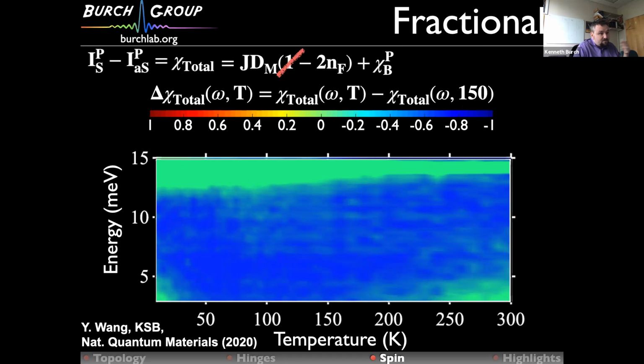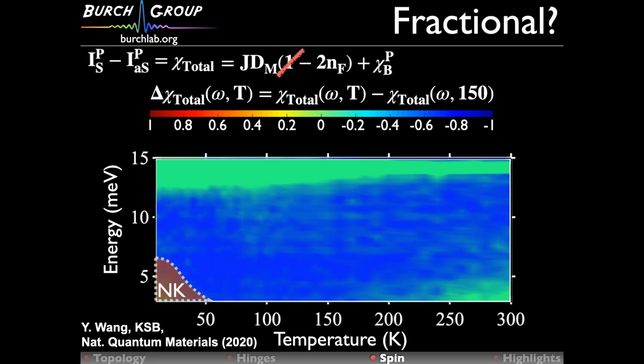And what we find is perfect agreement, except of course near the phonon, because there's no phonon in their calculation, and also in this small region at low energies and temperatures. And that enhancement in susceptibility, we believe, is coming from the non-Kitaev terms contributing to the response. And so that's how we came to believe that there's very strong evidence here that we have fractional excitations in this system. So you're looking at the gamma point, right?